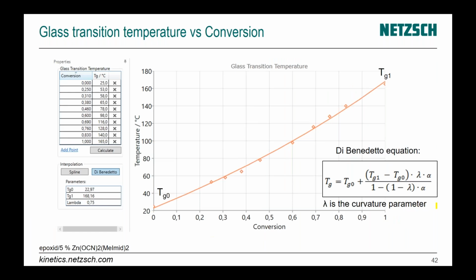Firstly, it is necessary to find the glass transition dependence on conversion. 0 here is conversion - 0 means the reaction is uncured, 1 means the reaction is totally cured. Here is the temperature for the uncured state and for the cured state, and there are a couple of intermediate points which should be measured additionally.